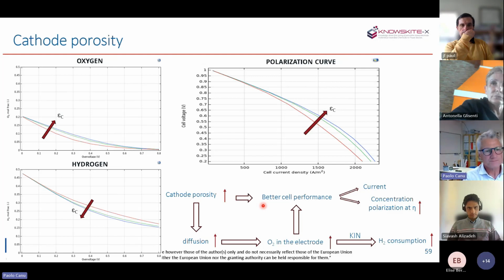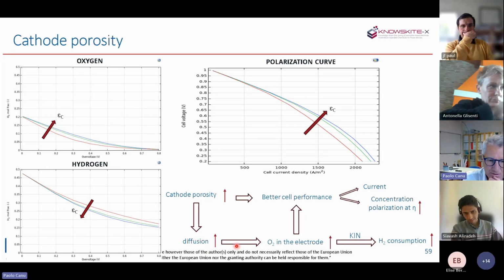That could be interesting, which is the impact of the porosity in the cathode. And we see that in terms of polarization curve, the porosity makes a difference. And that could also be seen as an opportunity to compare with experimental polarization curves and see the impact of having a higher or a lower porosity in the synthesis. Again, the porosity is expected to impact the diffusion, which means how easily the oxygen can penetrate the cathode and then support the electrochemistry, improving performance and then the current.